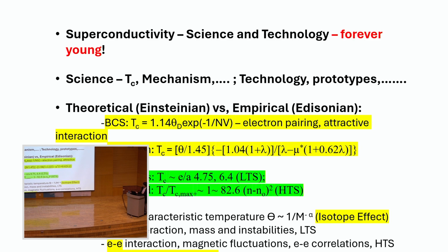There are several interesting forms of the BCS theory, but the modified form is the McMillan formula, as indicated here. It's the most used formula. I should mention there's a mu star here. This lambda is the attractive interaction, the electron-phonon interaction. Mu star is the Coulomb repulsion. I mention this because right now, for room temperature superconductors, people all thought it's safe, it's already solved, and they all said it's an ordinary electron-phonon superconductor. All you need is just the lambda, electron-phonon.